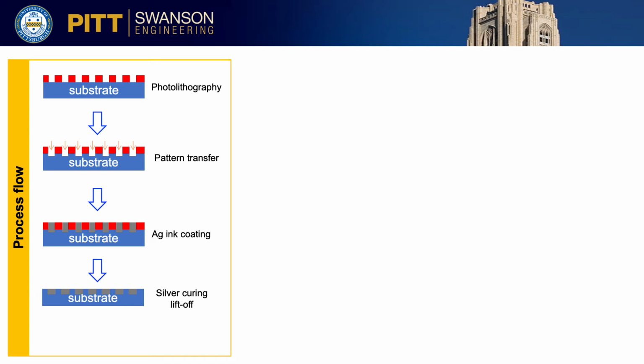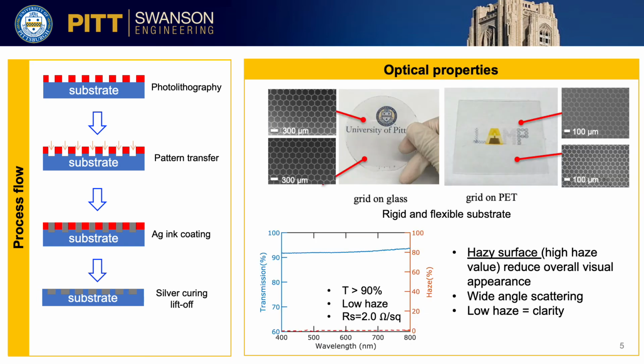This ink can achieve conductivities up to 90% of bulk silver with low annealing temperatures, which is a direct replacement for nanoparticle inks and metal paste. After curing and photoresist lift-off, we can get the fully embedded microgrid within the substrate. On the right figure, we can see the photo and SEM images showing the nice and uniform grids all over the substrate, including rigid glass and flexible PET.